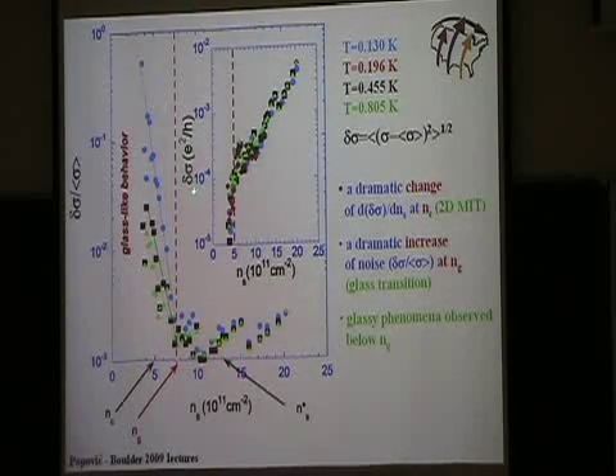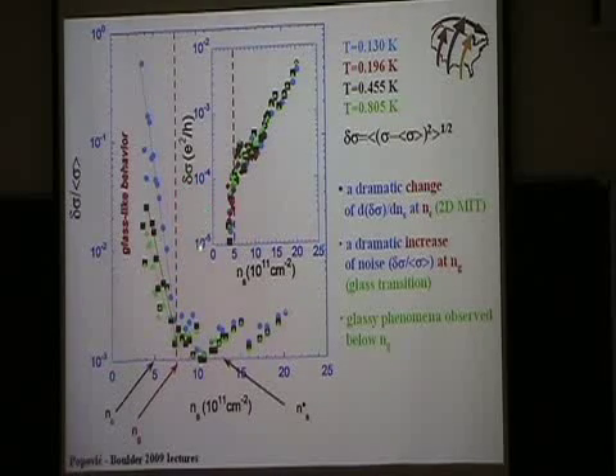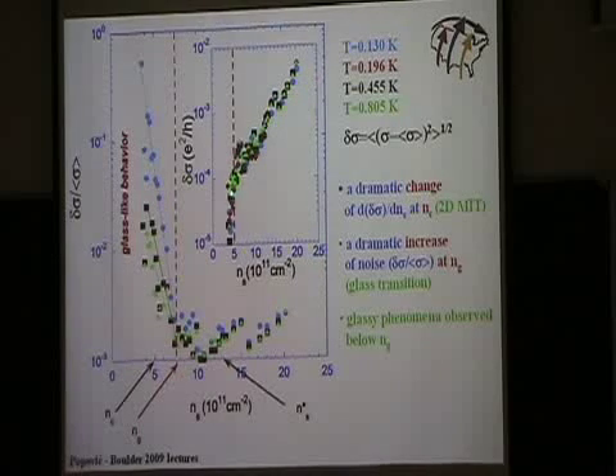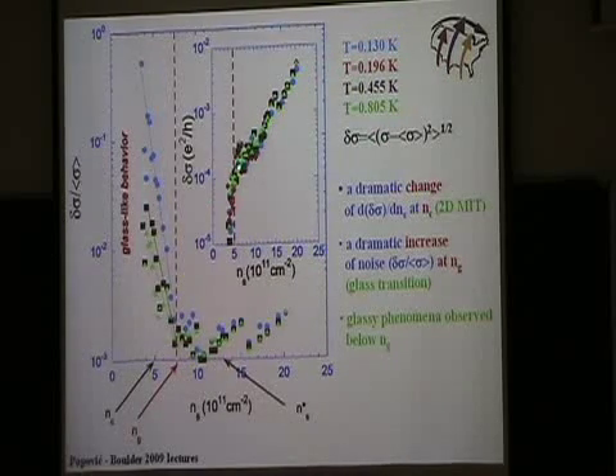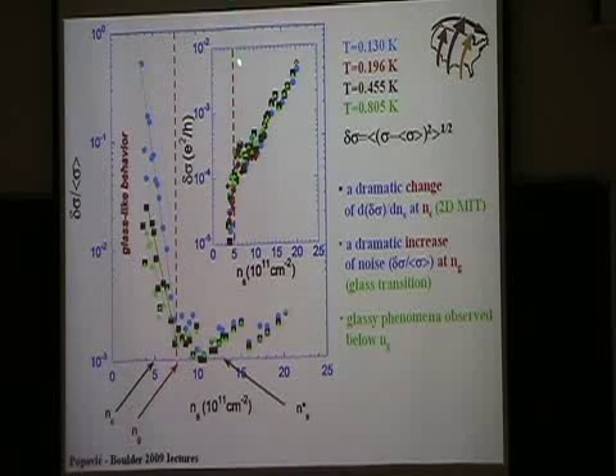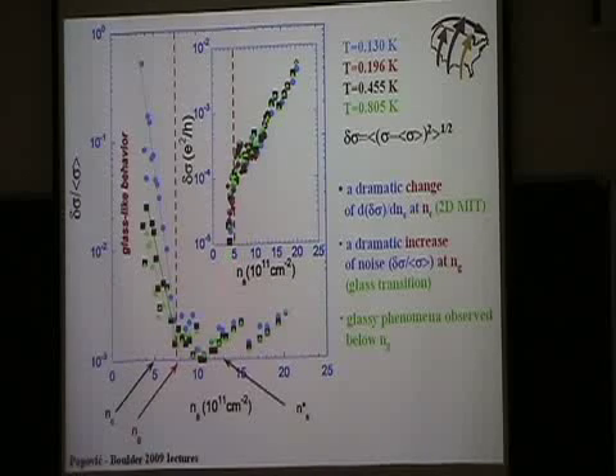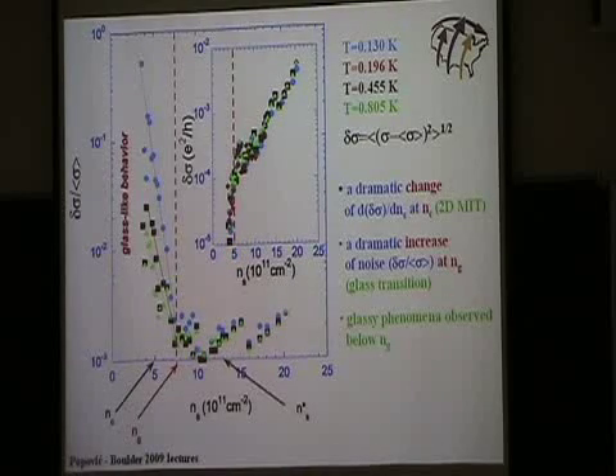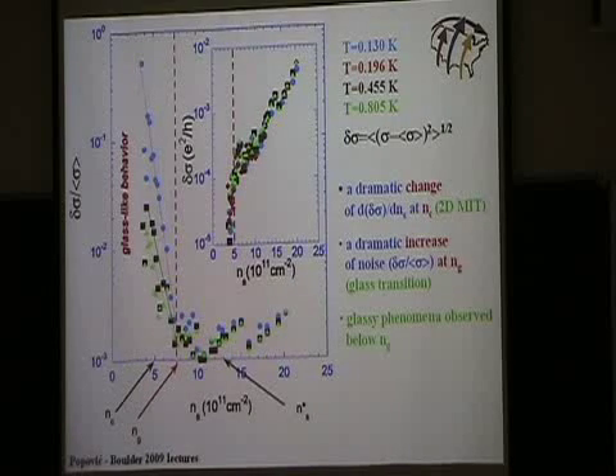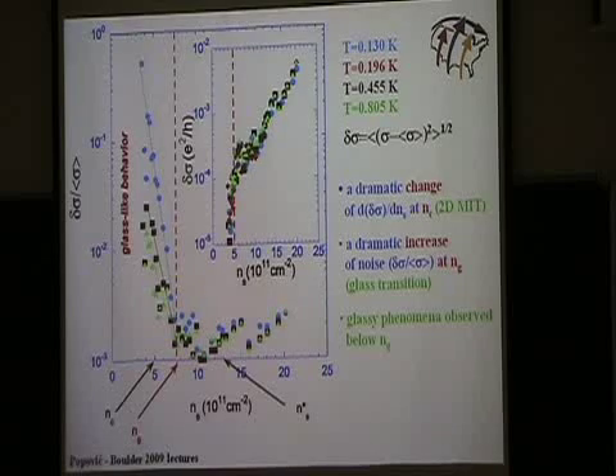If you look at the variance or standard deviation itself as a function of density, for different temperatures, we did not see any temperature dependence, at least in this range, but you can see that this slope changes dramatically exactly at Nc, the critical density for the metal-insulator transition. So it also kind of makes sense, it's plausible because the electrons are becoming strongly localized, so it's more difficult for them to move around. But that's all I can tell you about that.